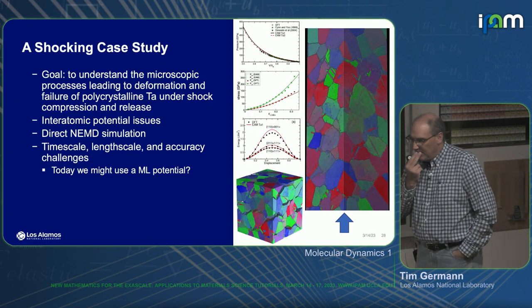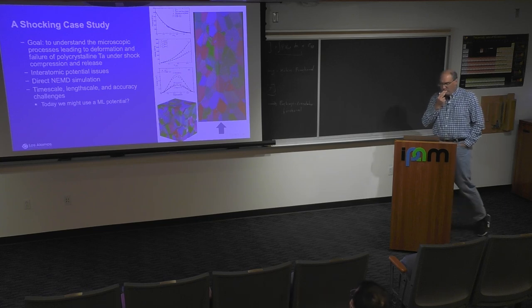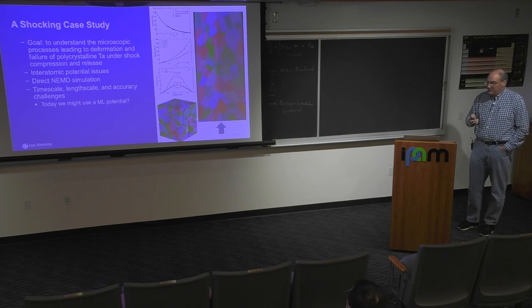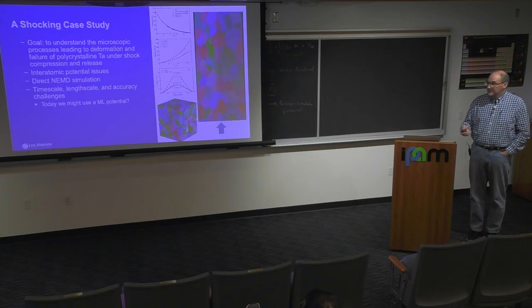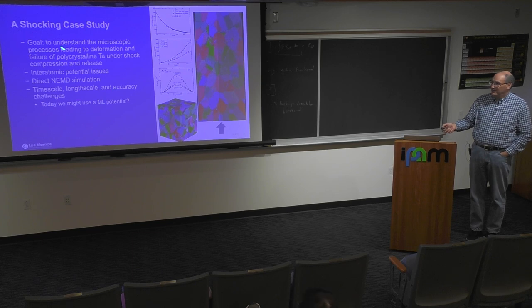Another example — high velocity shock compression. Maybe a decade ago there was a lot of interest in studying Tantalum and its response to shock wave compression: you hit it at high velocity (kilometer per second), a compression wave runs through the sample. When it reaches the free surface a release wave forms and the sample goes back to zero pressure. If you impact one sample into another, you get release waves from both ends that cross and the material is pulled into tension — it can fail. Those are the fracture surfaces shown here. Today, people paying us would want us to use a machine-learning-based potential, but when we started we looked at the available EAM potentials in the literature. They all predicted tantalum would be HCP after 35 to 65 GPa, whereas experimentally it remains BCC up to much higher pressures.